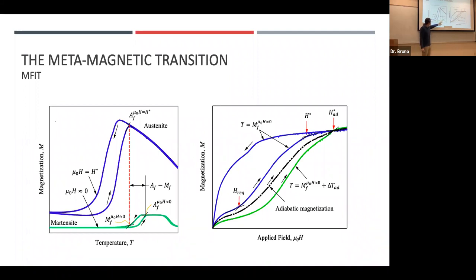If we apply a larger field, we're actually going to decrease these transformation temperatures. So the green curve here is, say, a very small field, like 0.05 Tesla or something. The blue curve would be like 7 Tesla, so a really large magnetic field. A fridge magnet, I think, is about 0.2 Tesla or something. You can imagine the really big magnetic field you need.